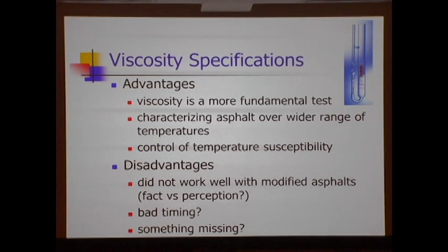It was perceived that the viscosity test didn't work too well with modified asphalts. Now, I'm not sure that's totally true, because there's a lot of viscometers that you can use, those straight wall tubes, which actually work very well with modified asphalts. And in fact, for many years, we had been using viscosity-type technology with modified asphalts. But I think more importantly, viscosity specs were sort of bad timing, and there was a feeling that something was missing.